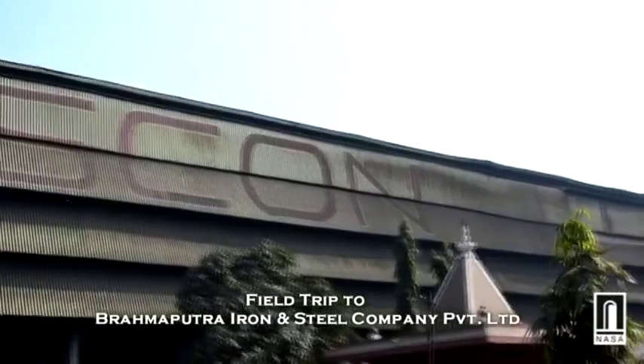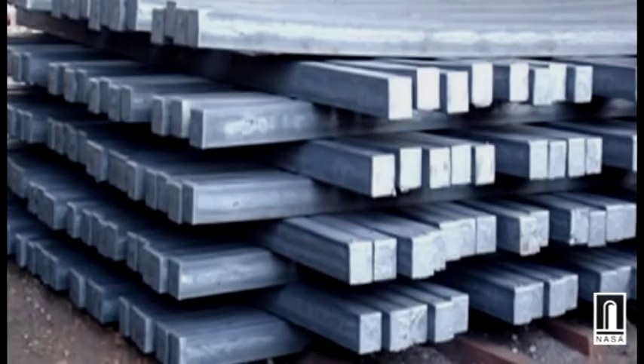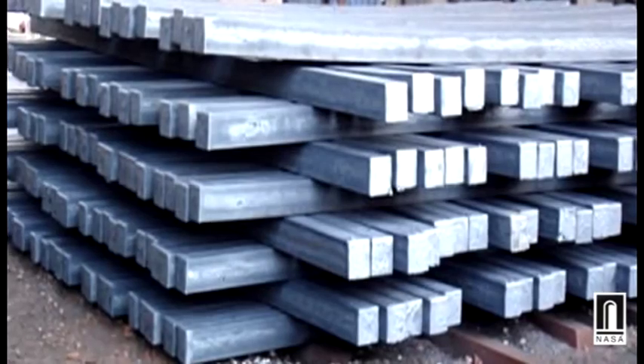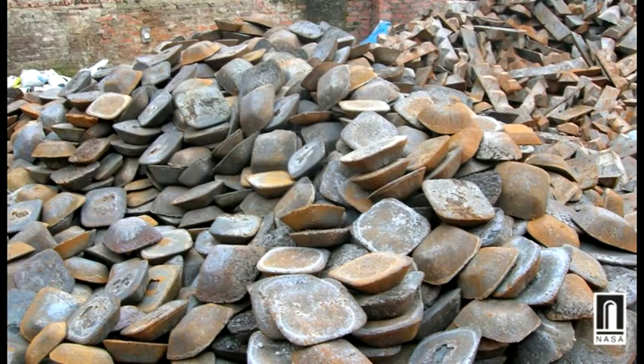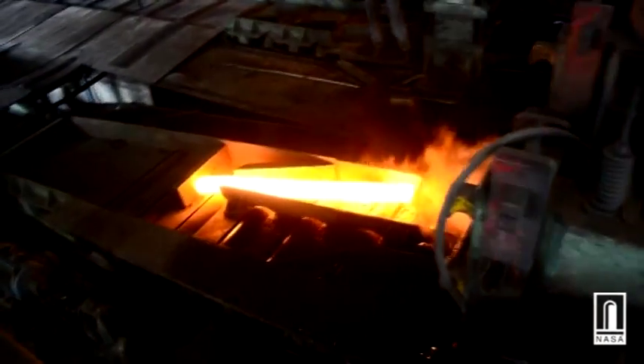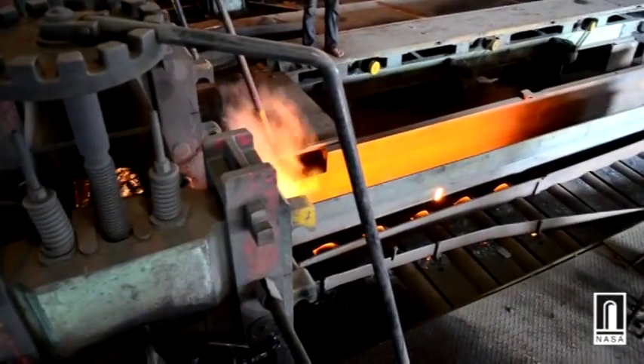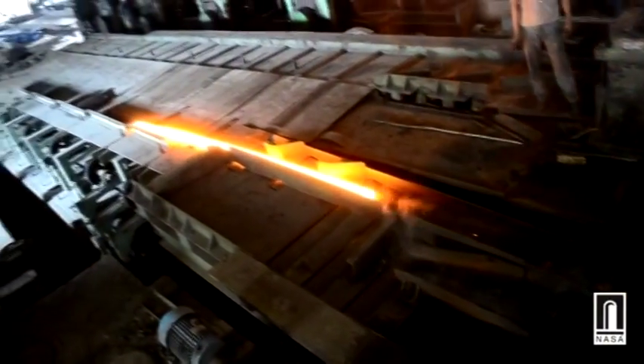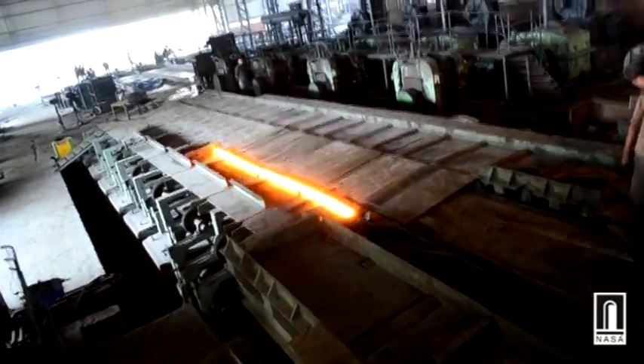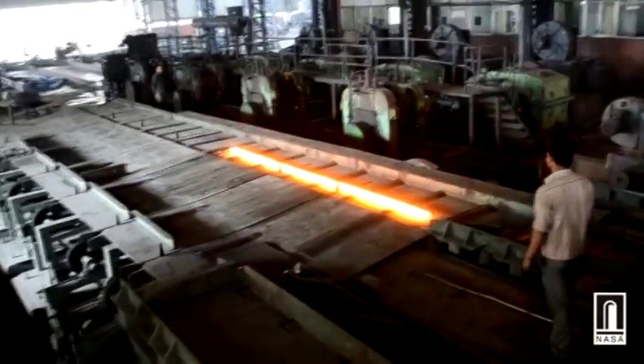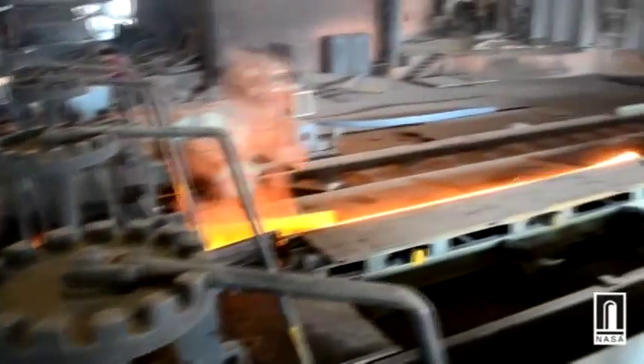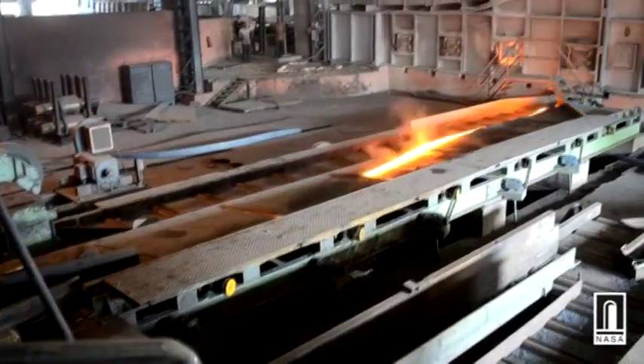The process of manufacturing of steel requires billets, which are manufactured with a combination of sponge iron, pig iron, MS scrap, and certain chemicals like carbon, manganese, sulfur, and phosphorus at different proportions. Once a billet is manufactured, it is cut into a length of 4 meters with a cross section of 102 by 102 mm and made to pass through a furnace with a temperature of 1100 degrees Celsius to 1150 degrees Celsius.